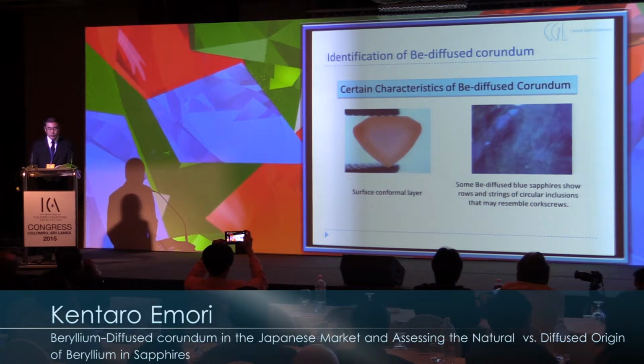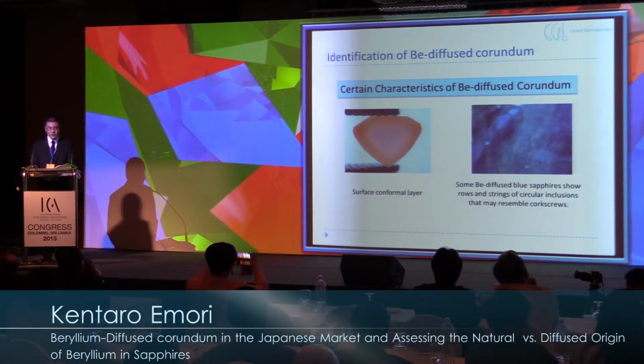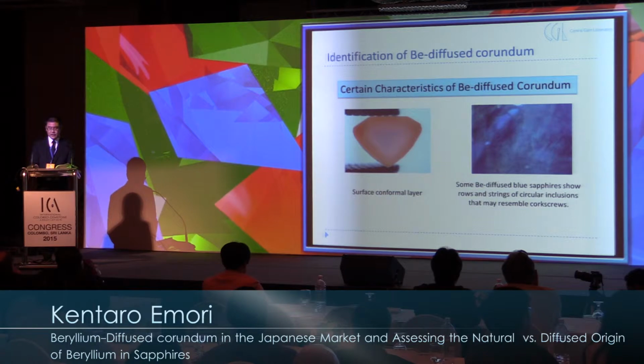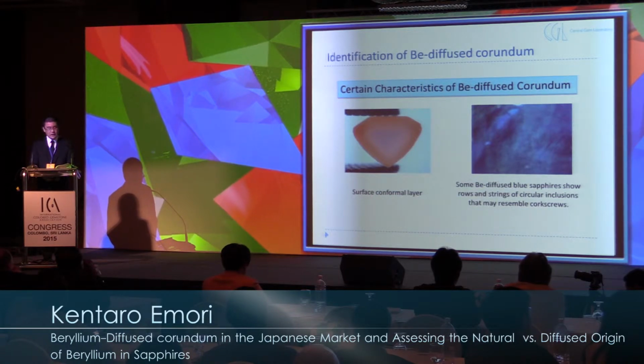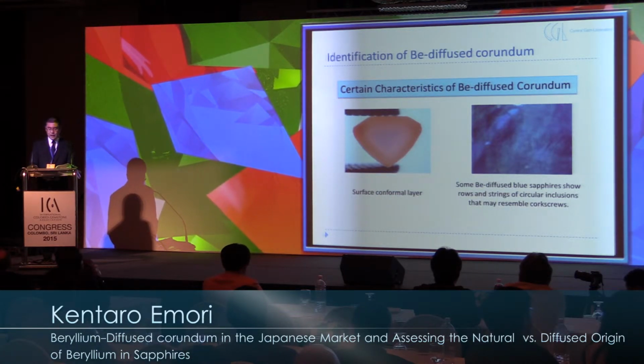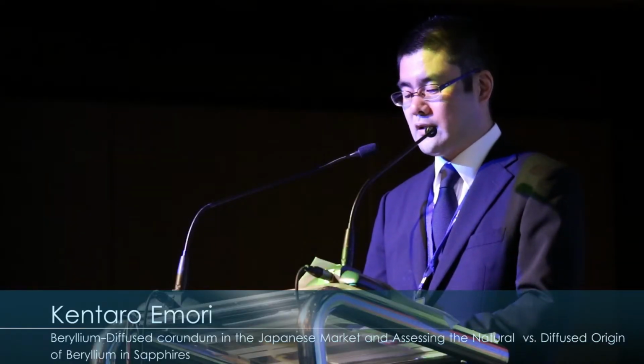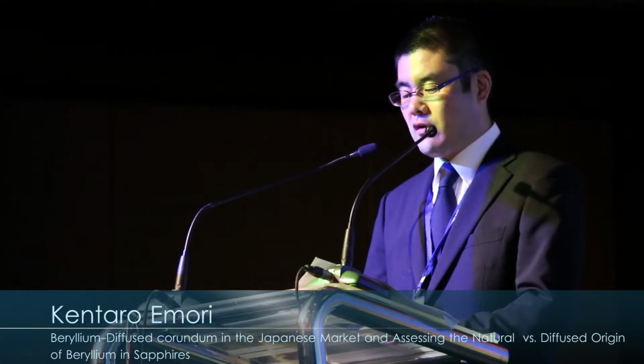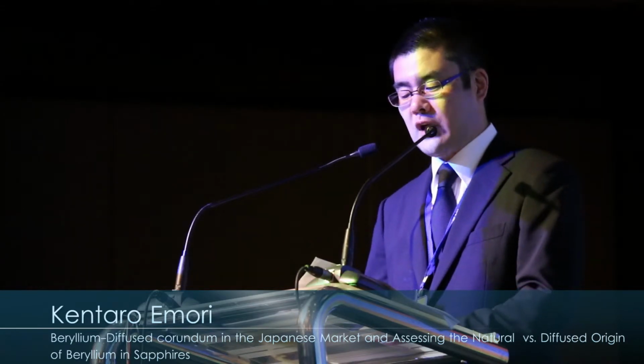We explain how to identify beryllium-diffused treatment. One of the characteristics of beryllium-diffused corundum is a surface conformal layer. A surface conformal layer suggests that this stone was treated and colored artificially. A surface conformal layer cannot be observed in blue sapphires, but beryllium-diffused blue corundum may have rows and strings of circular inclusions that may resemble a corkscrew like this photo.